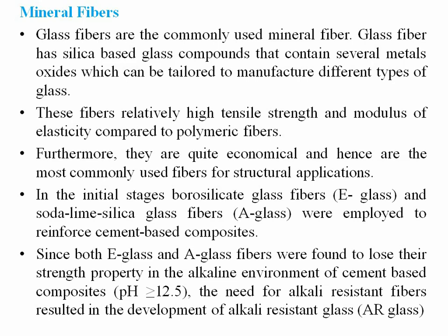In the initial stages, borosilicate glass fiber, called E-glass, and soda lime silica glass fiber, called A-glass, were employed to reinforce cement based composites. Both E and A-glass fibers were found to lose their strength in the alkaline environment of cement based composites, where the pH is greater than or equal to 12.5.